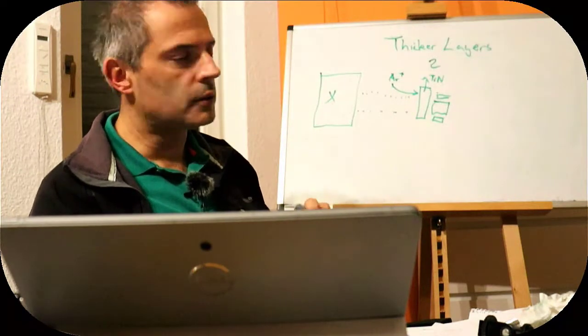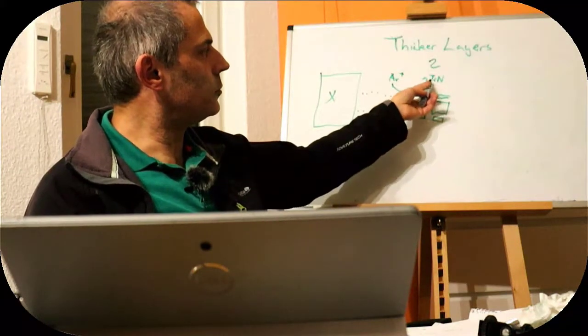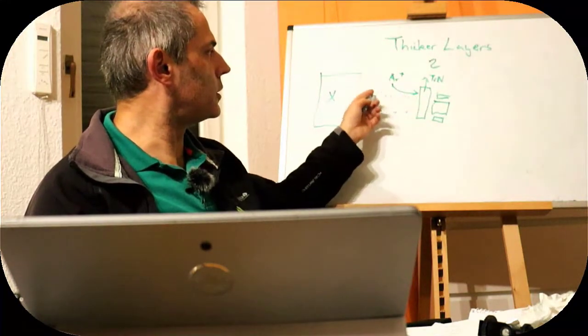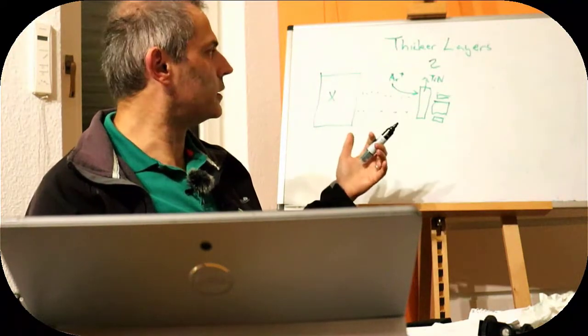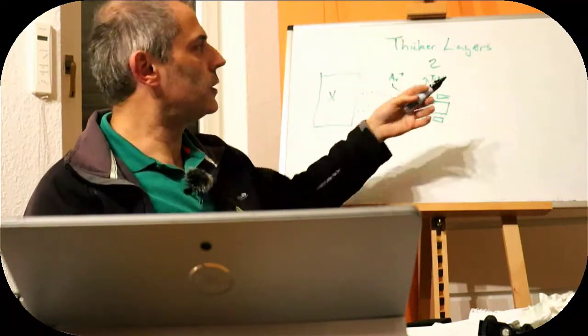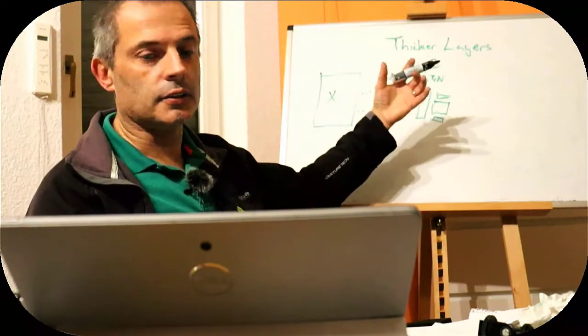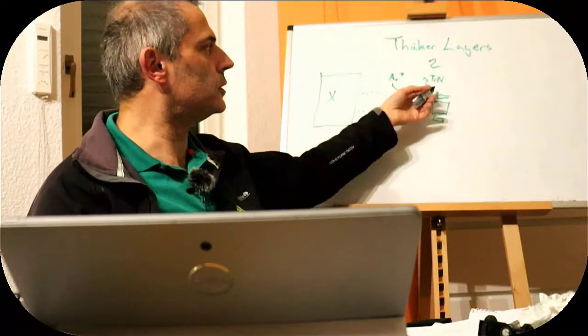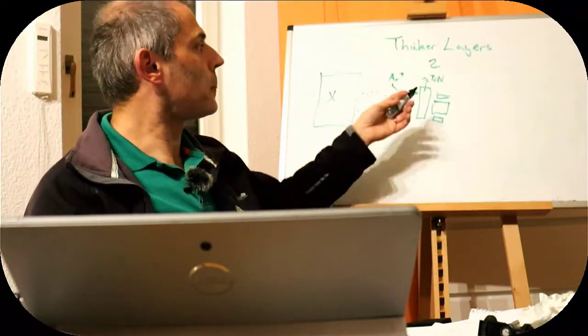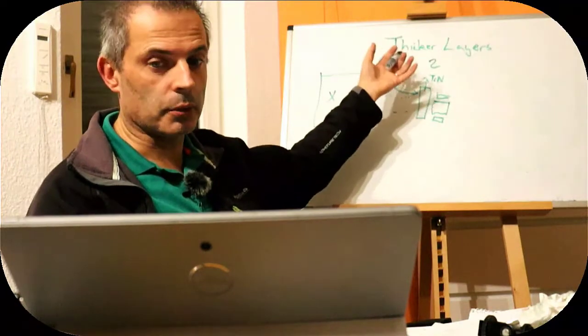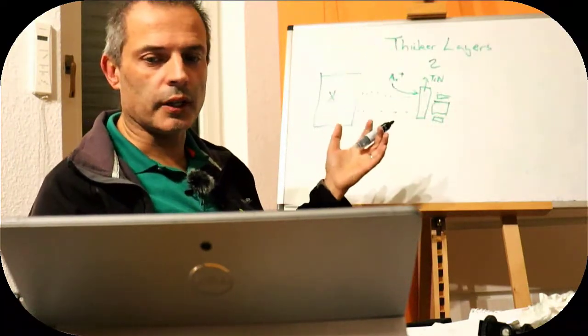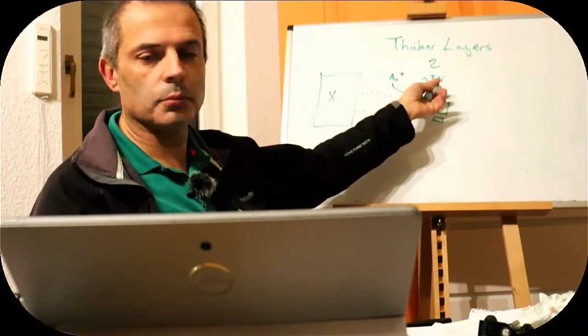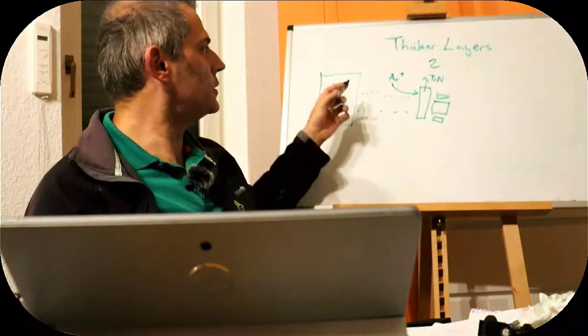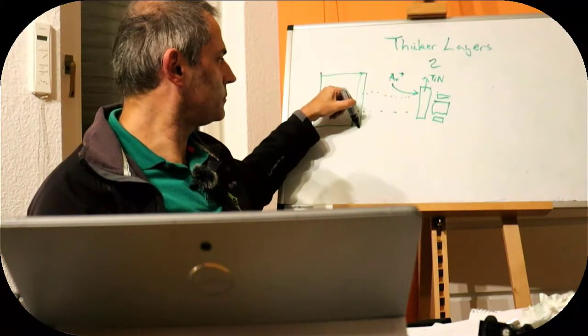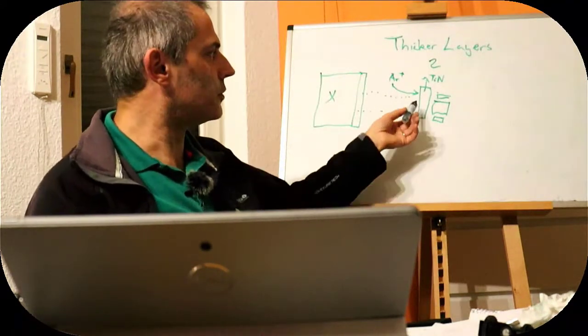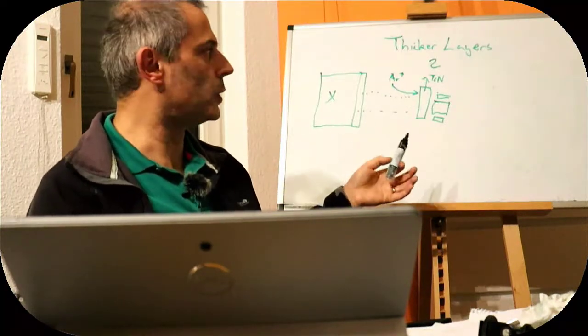But there's a problem with this. The problem with this is that the titanium is fine because it's going to go in a straight line and stick where it gets to, and if it goes anywhere else it will be lost. The nitrogen, on the other hand, is possibly going to connect to another nitrogen atom and form nitrogen gas, and maybe get pumped away into the pumps as gas. The problem with that is that the stoichiometry of our film, that started out perfect, is not going to be the same when it gets to here, because some of one or the other component will be lost on the way, typically the nitrogen.